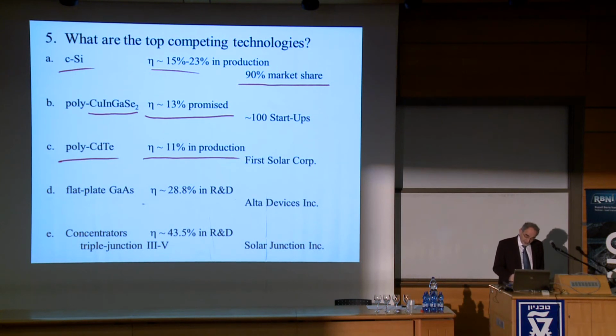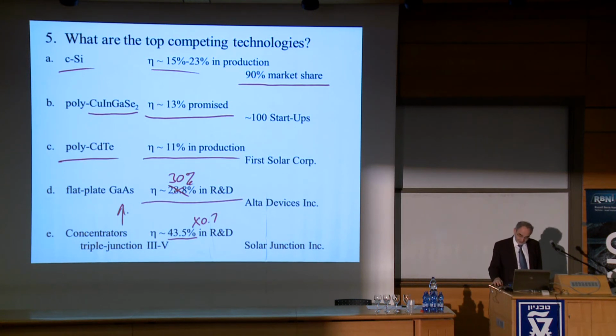Flat plate gallium arsenide, I showed you. Well, I guess this is out of date now. A dual junction is now 30%, which is pretty good. Triple junction concentrator, it looks higher. Actually, I think they've now reached 44%. However, you have to be very careful when you evaluate concentrators. They're using only 70% of the sunlight, and so the efficiency should be multiplied by 0.7. And in that case, it looks similar to the flat plate technologies.